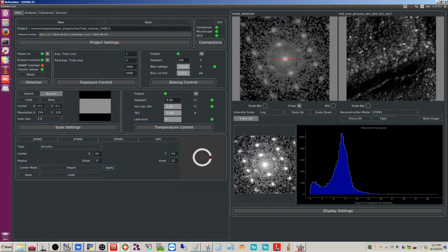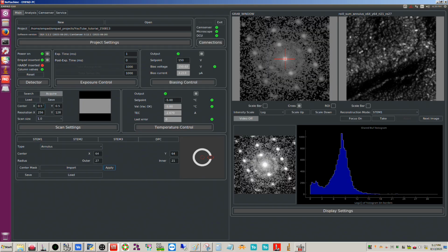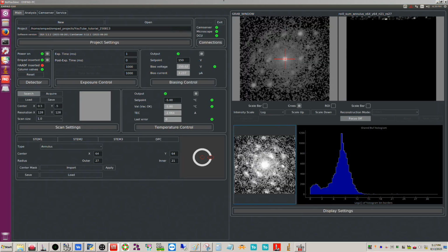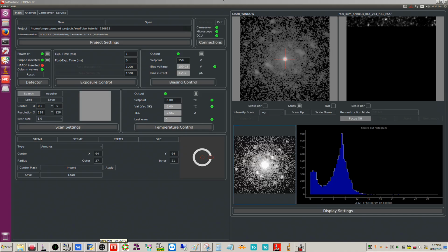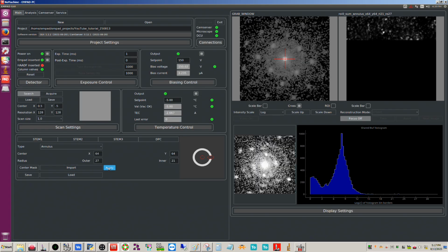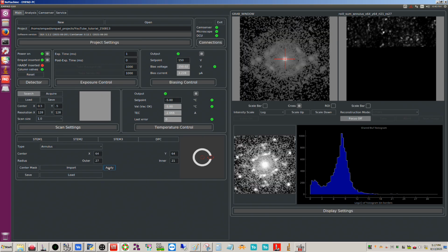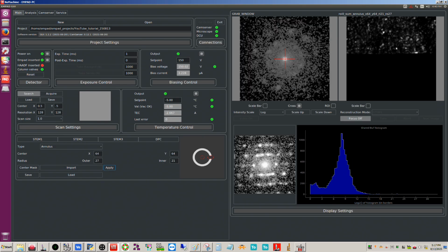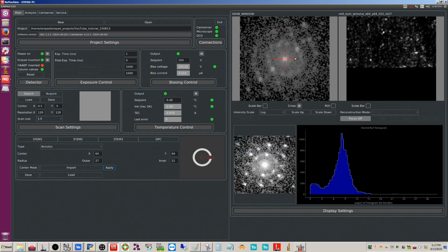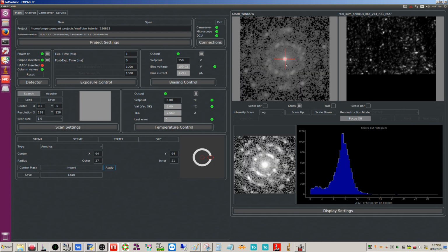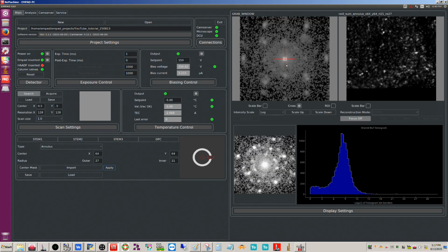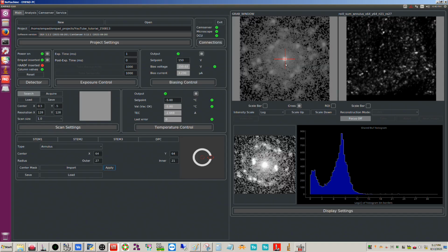So we'll go ahead and use that for our reconstructed image. So let's go back to search and click focus on, and let's see how this looks here. If we hit apply, yeah, so that's exactly what that is. So now this is like a texture tool. So we can see grains that have strong 111 reflection here. So it's pretty neat. So you can isolate d-spacings with this,